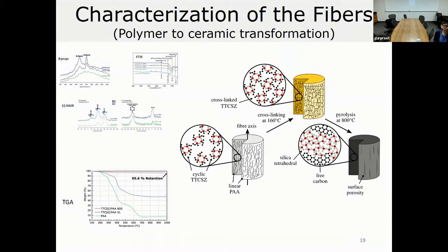For example, we use Raman to study the evolution of the free carbon phase. We use FTIR and NMR to establish the cross-linking mechanisms, and TGA to look at the polymer to ceramic yield. And then based on these analyses, you can propose these kinds of mechanisms or make these schematics.